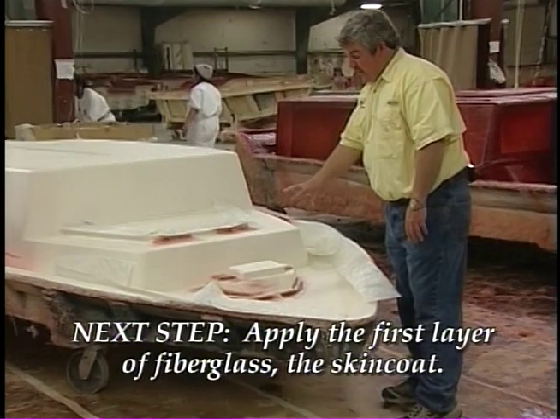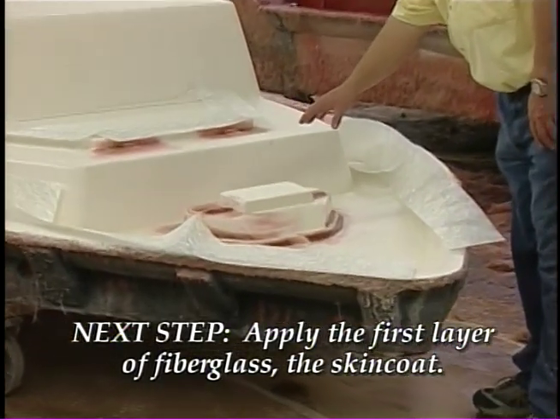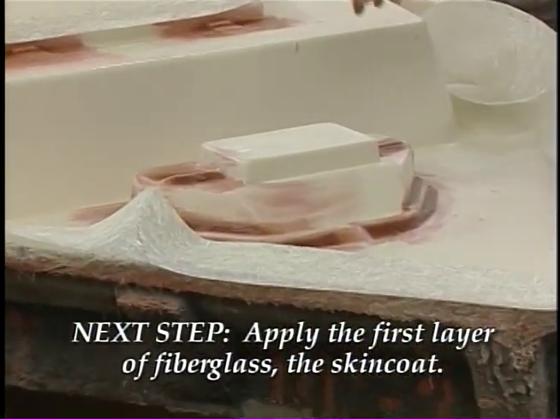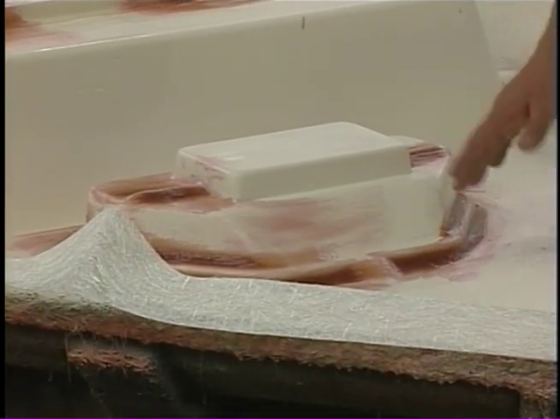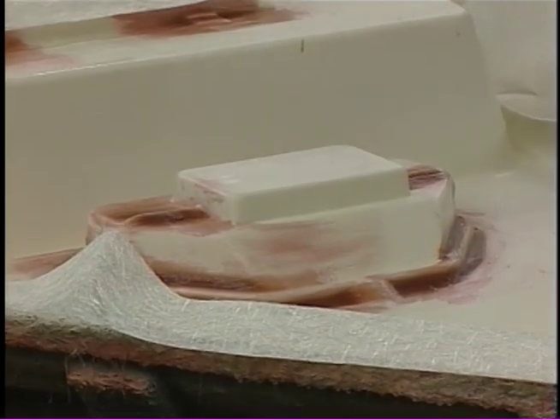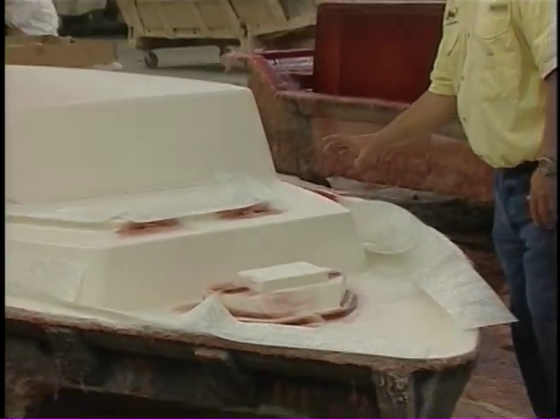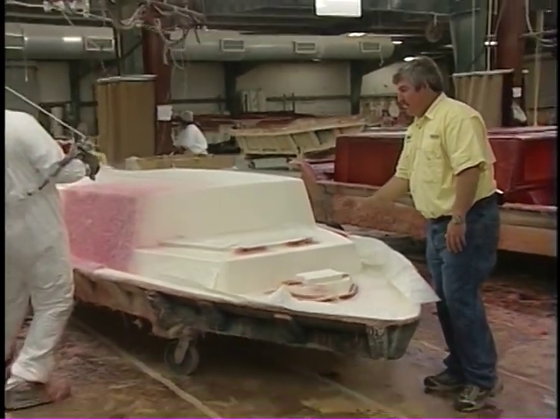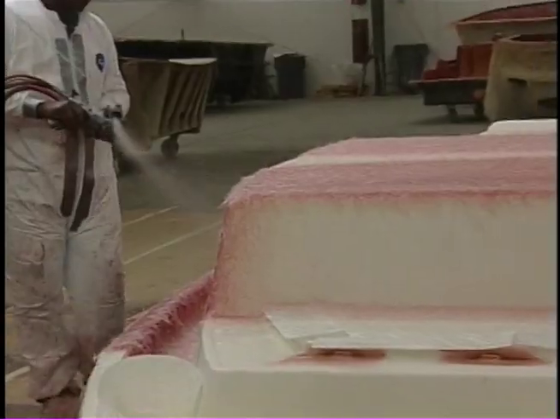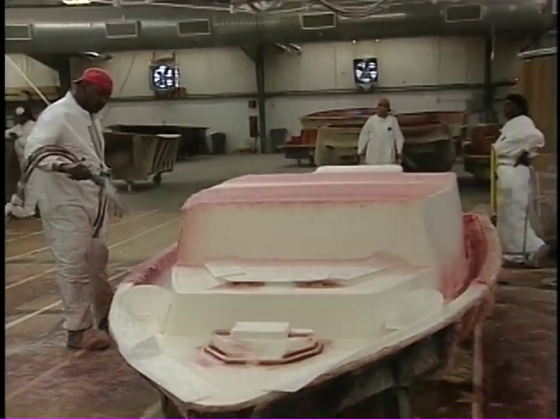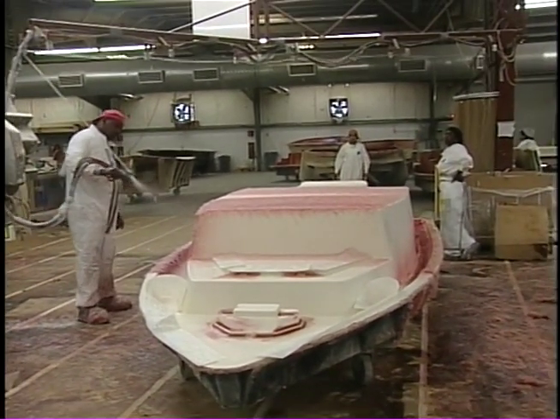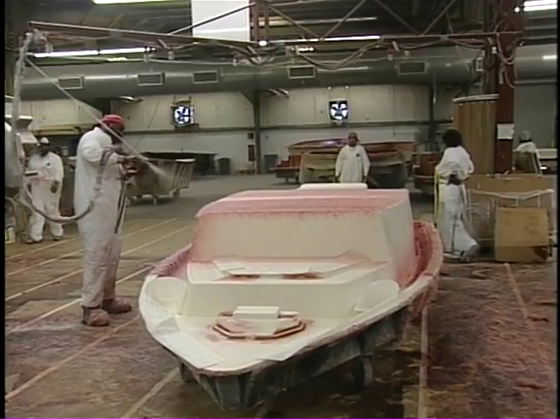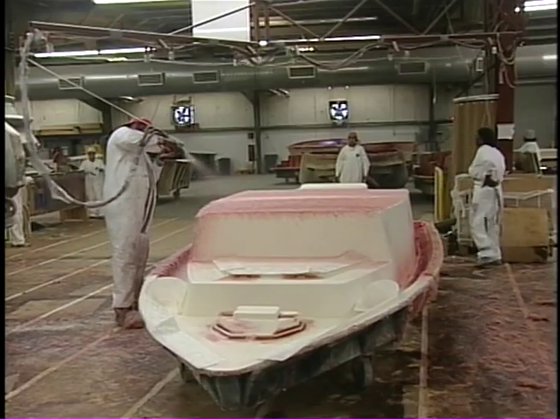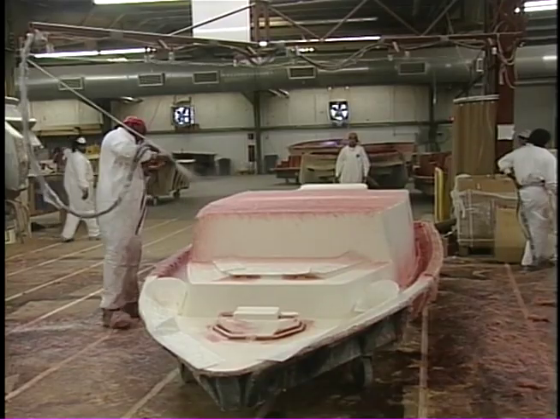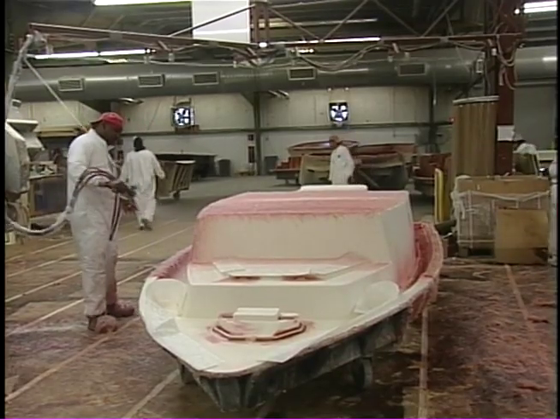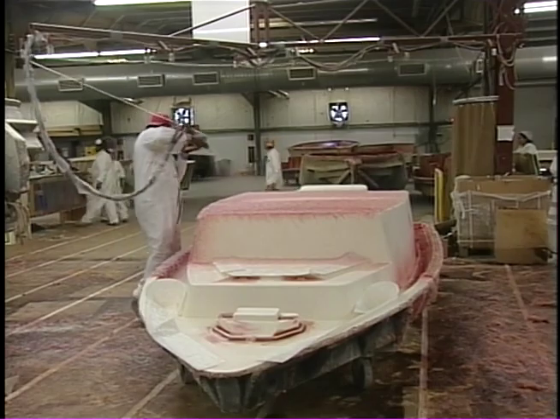We've gel coated and put our filler in, and we're getting ready to do the skin coat on the boat. And when he puts this glass on, this putty that we put in will soften that radius. Make sure that glass is able to roll down and gets a real tight finish so we won't have an air bubble later, have that eggshell finish get cracked. And it's important that this skin coat be done as soon as the gel coat dries. As soon as that gel coat area is dry enough that you can touch it with your hand, we come right back with this skin coat to make sure that we get a really good chemical bond as well as a mechanical bond. That ensures that we don't have blisters later on.